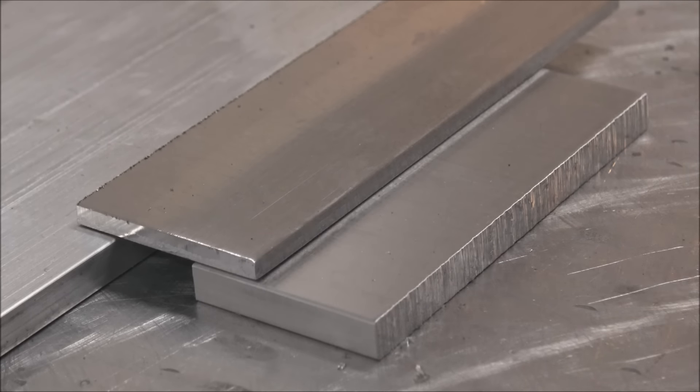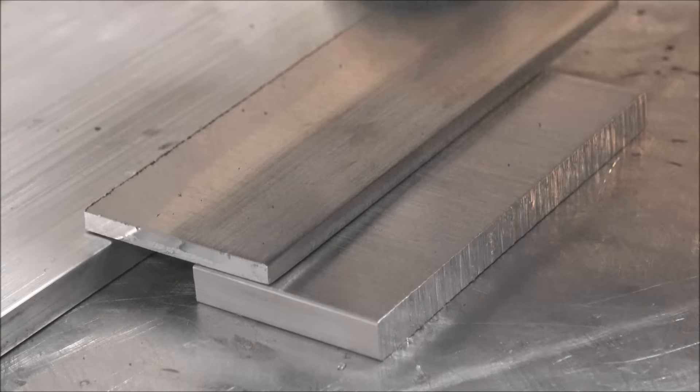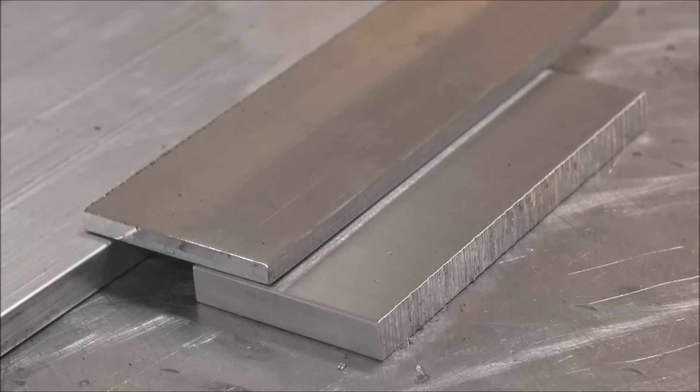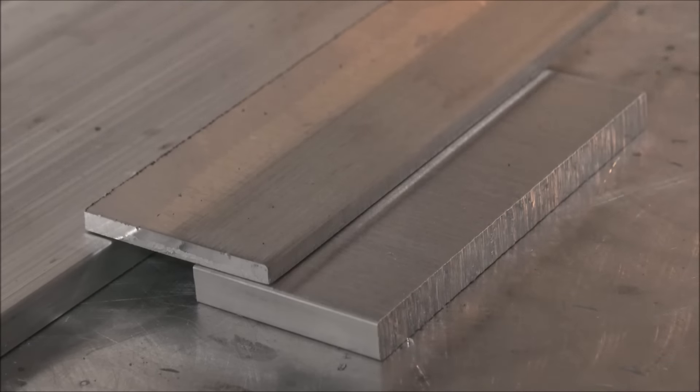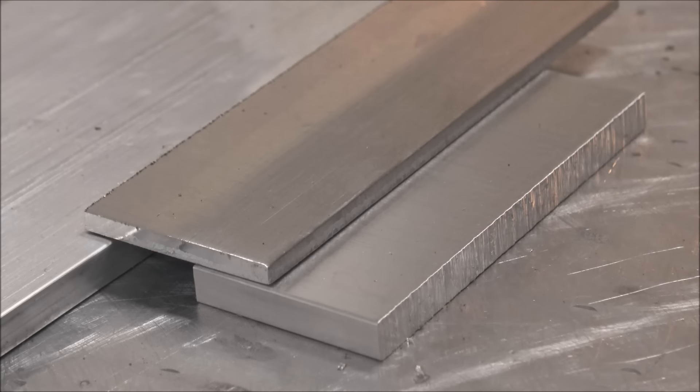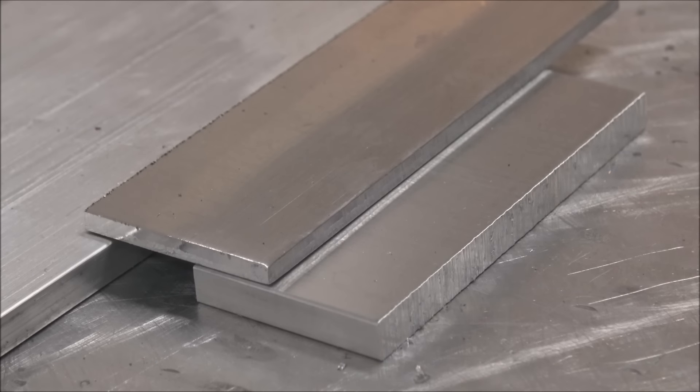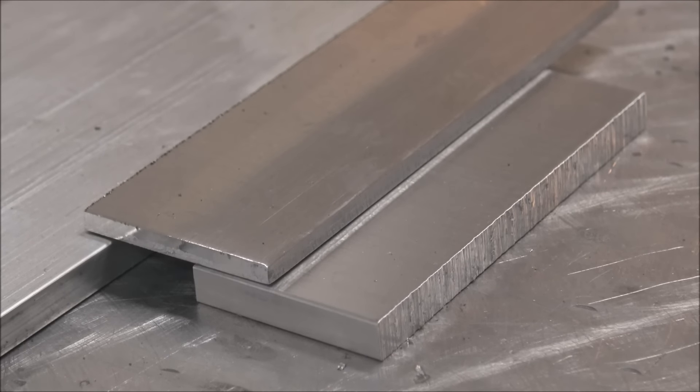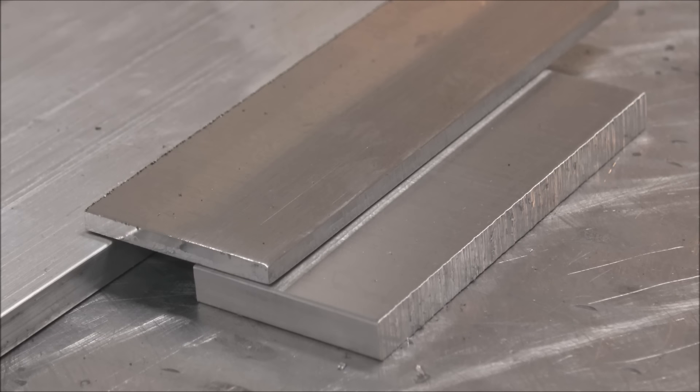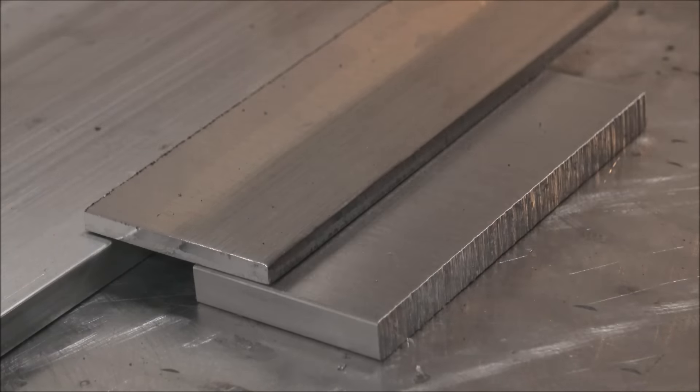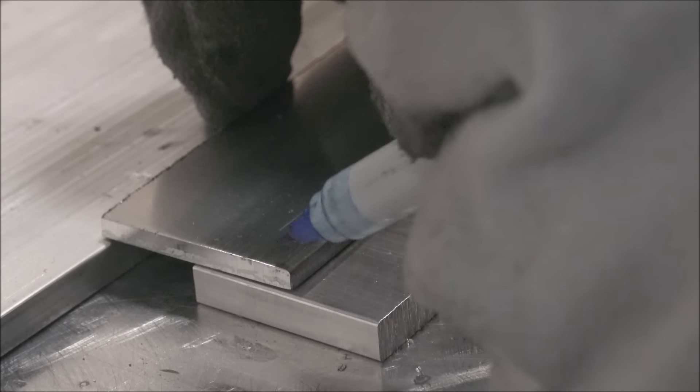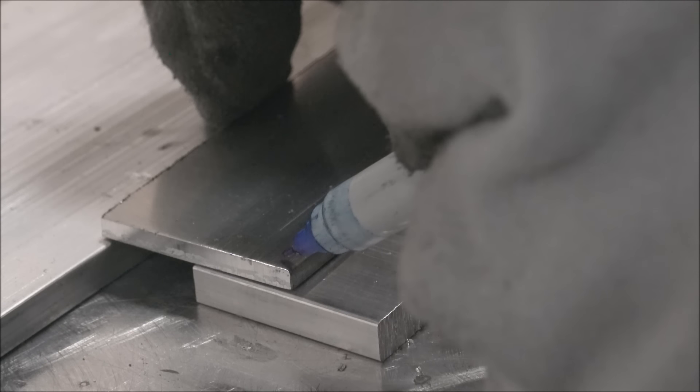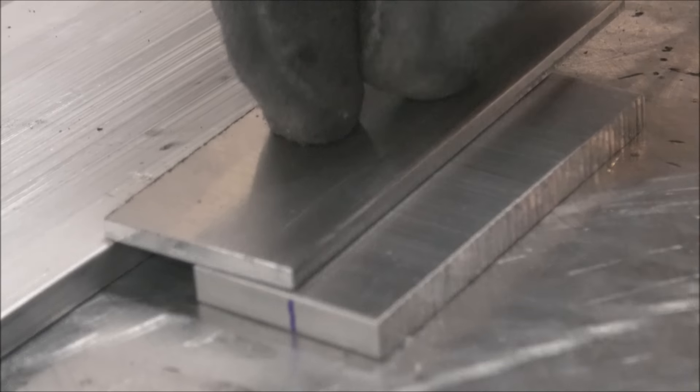And you can do lap welds too without filler rod. This is actually a really good practice if you're having problems making your lap welds look nice and consistent with filler rod. This helps you isolate the problem and a lot of times it's where you're pointing your torch. Try to pay attention to how much of this top piece I'm actually burning back. I don't stay out here, I come way back over on it so it acts as the filler.